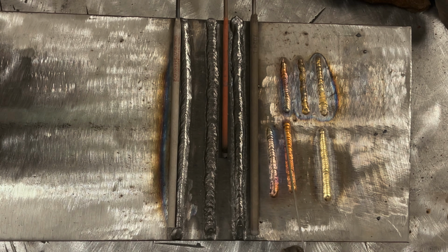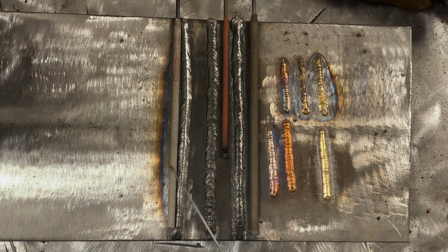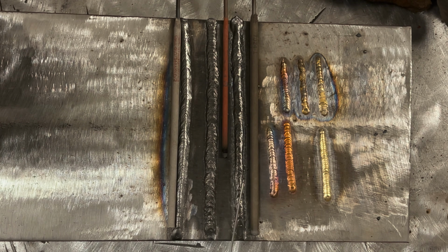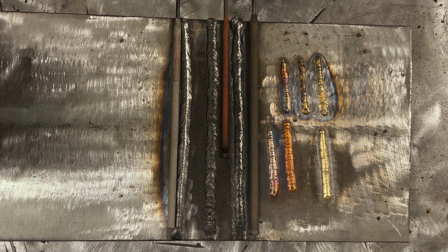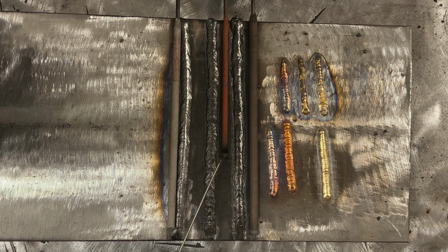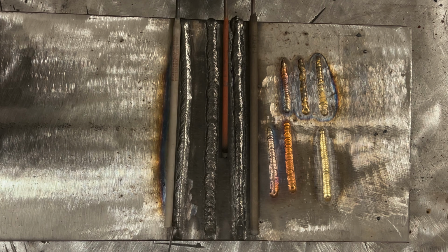Now, there's a couple interesting things to note about this. First off is the 70-24 rod. All the beads are the same length, but you can see how much is left of this rod still. So it didn't even burn anywhere near half. The 60-10, to get this length of weld, burned up probably better than half, and then the 70-18 burned up, I don't know, 60% of the rod or so.